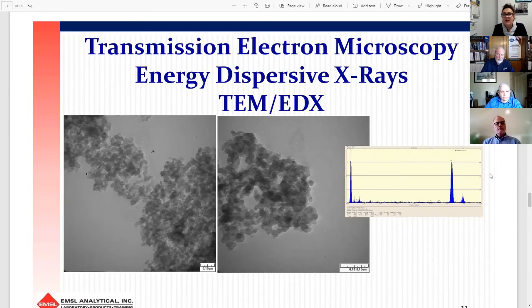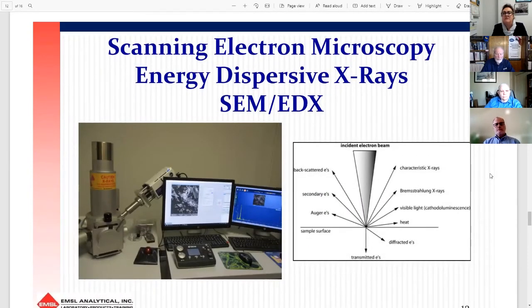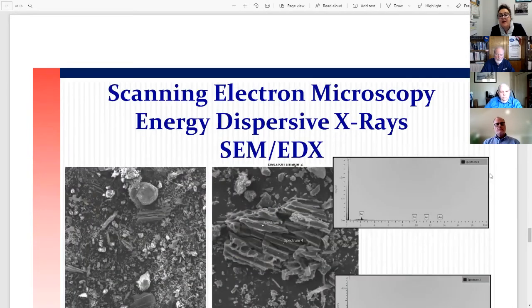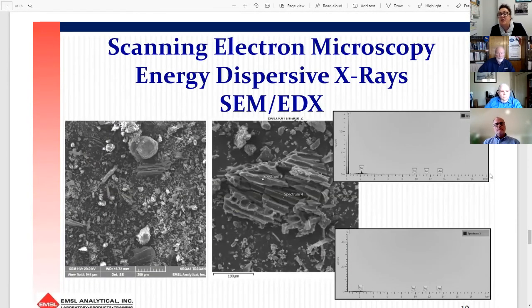Now on the next slide, it's another auxiliary method, scanning electron microscopy, which also is a high magnification technique, not as high as the TEM, and it uses a different type of interaction between electrons and samples, so you get different types of images. On the next slide, I believe I have a picture of char and how char looks under the SEM. So you can see the morphology, you can see the porous structure, you can see the size. So this is about 100 microns. You will see this by PLM, but not with as many details.